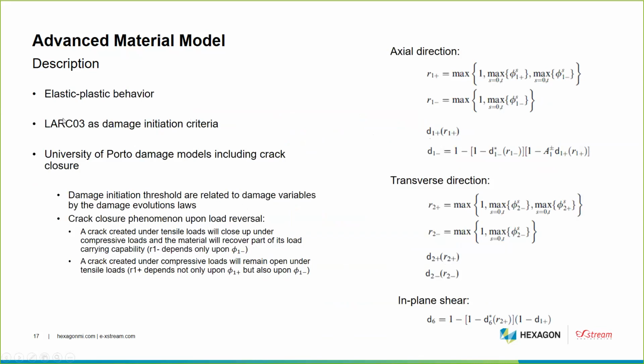So once we have defined and computed the damage initiation criteria, we need to propagate the damage. So we need some damage propagation law, and in this case, we have coded the damage propagation law proposed directly by Professor Camanho. That's what is called here the University of Porto damage model. And this damage model includes the crack closure. So the damage initiation thresholds are related to the damage variables by the damage evolution law. The damage initiation threshold is LARC03, and then the damage evolution laws are the ones proposed by the University of Porto.